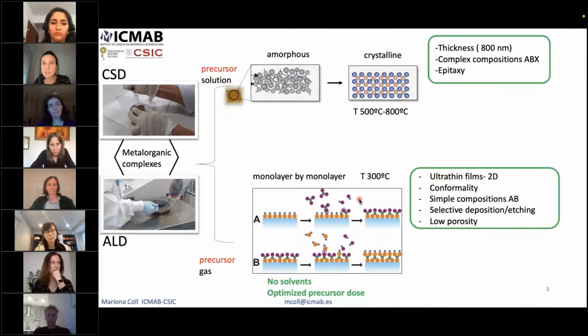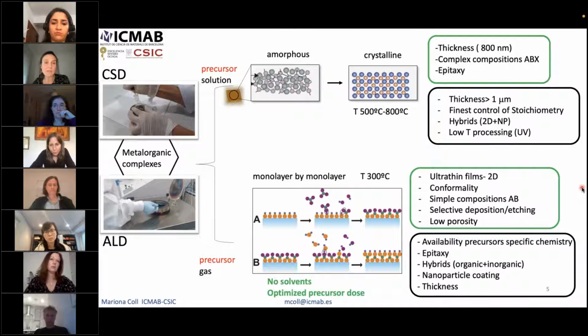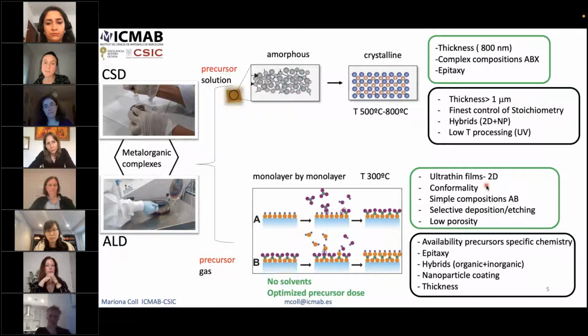I tried to summarize the advantages of both techniques, highlighted here in green, but also some of the demands that can be interesting to achieve for these correlated oxides. I would like to emphasize the epitaxy and the preparation of complex compositions, and of course the potential of atomic layer deposition to prepare ultra-thin films, two-dimensional materials, and to have selective deposition and etching, which is really important to simplify the lithographic steps that we have right now. This is quite well established for binary materials, and what we are trying to do in our group is to achieve this degree of control in complex oxides.